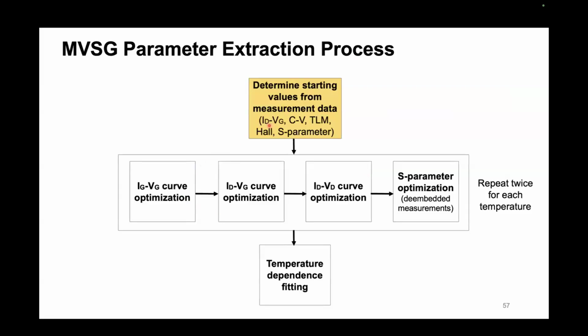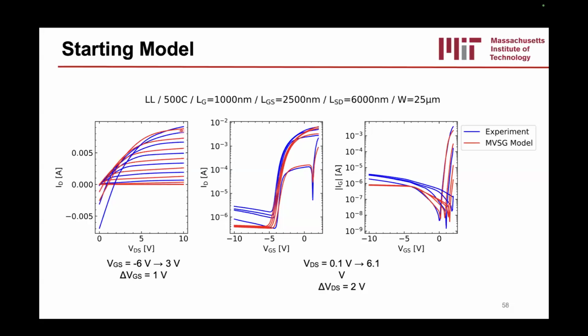What we did here is we started off with an initial guess for these parameters. We've been doing this modeling for a while now, and from a lot of the device level measurements, like the CV, the TLM, and the Hall, you can get a pretty good guess for a lot of what these parameters should be. And so if you do that and you look at 500 Celsius for, in this case, a long channel device, a 1 micron device, you can see the blue is the experimental data and the red is the model data. You can look at the output, the transfer, and the gate leakage characteristics, and they're not too far off if you have a pretty good guess.